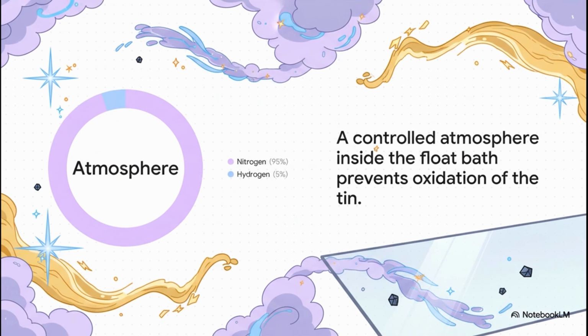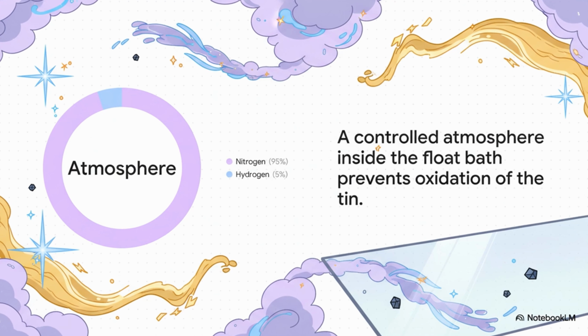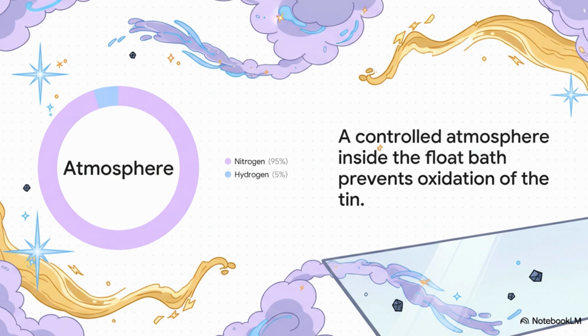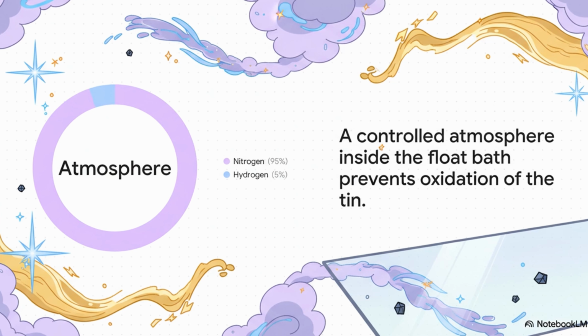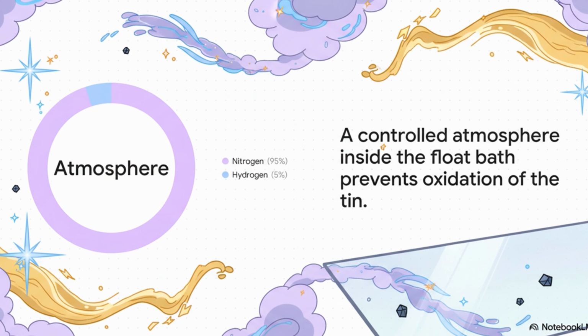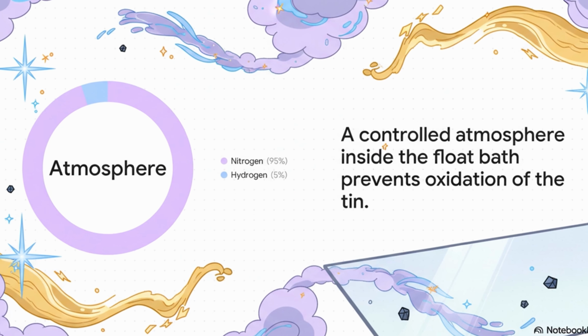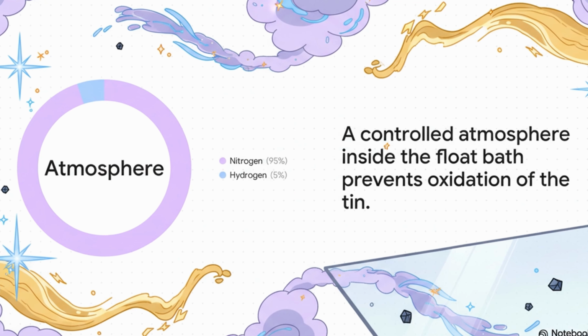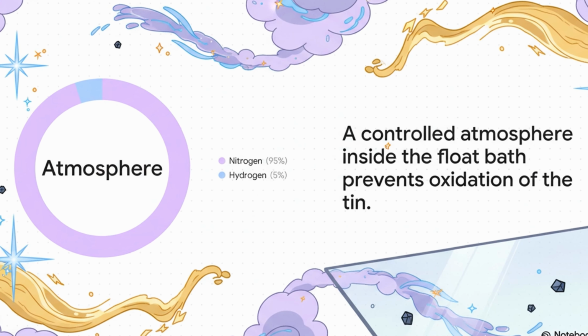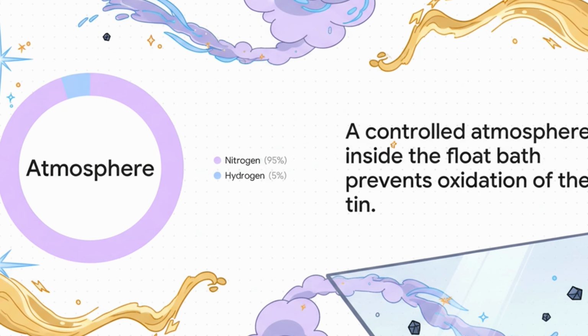Okay, one last critical detail. Hot tin and oxygen are mortal enemies. If they meet, they form tin oxide, which creates defects on the glass. The solution? Get rid of all the oxygen. The entire float bath is sealed in a controlled atmosphere of nitrogen and hydrogen. That little bit of hydrogen acts like a security guard, seeking out and combining with any stray oxygen molecules to keep the tin surface absolutely pristine.